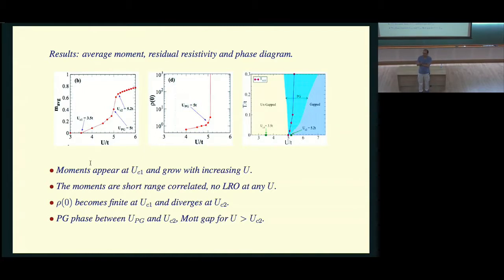What would you examine to look for this? You would get an anomalous Hall response, because we haven't computed it. In the molybdates, there is an anomalous Hall. In the real materials, both the iridates and the molybdates, there are materials which show spontaneous anomalous Hall related to spin chirality. To say that they're disordered is a bit disingenuous because they are on a tetrahedron. There is a certain short range correlation to it. It generates a chirality, as a result of which there is a spontaneous anomalous component to the Hall that will show up here. Whether this survives or not is a big issue, given that you're in a metal. But modulo that, yes, you would see that.